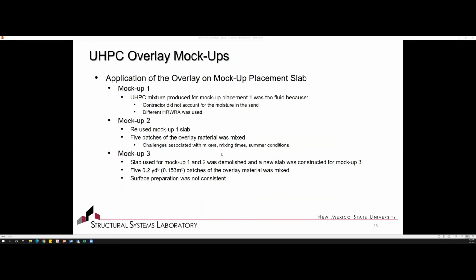So we started out with just planning for one mock-up. We ended up doing 3, and this comes into some of those challenges that we see as we take the stuff from the laboratory and take it into the field. So the first mock-up, essentially we were there. We worked with the contractors to cast the UHPC. However, we had some issues with that.